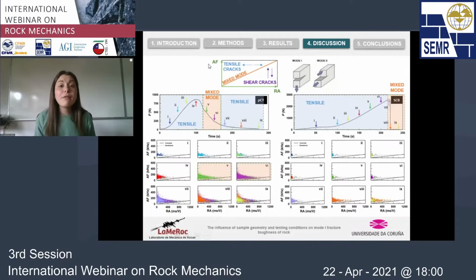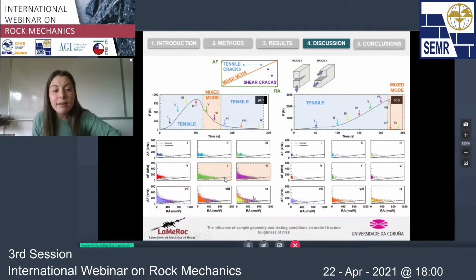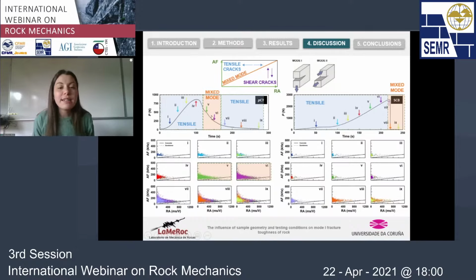As I have said before, we have used the average frequency and the rise angle to classify events into tensile or shear cracks or mixed mode. What we have seen was that the major part of the experiments were performed under pure tensile conditions, but at some point, and we can see it here on these graphs, in green and purple, these events are more located on this line, which is marking the threshold between the two modes. At this point, the events are located on the line, and some events even fall on the shear field. So although the experiment is performed under pure tensile conditions, we still have a state of mixed mode.